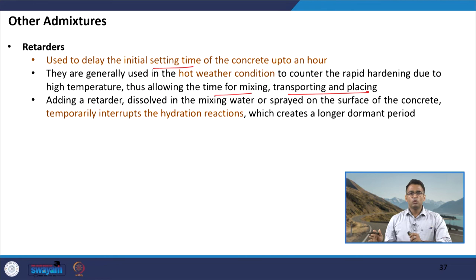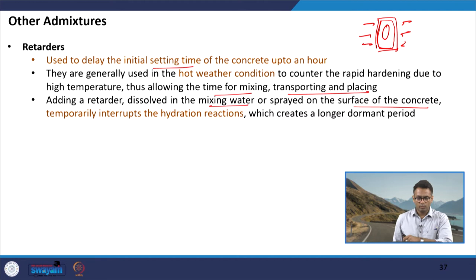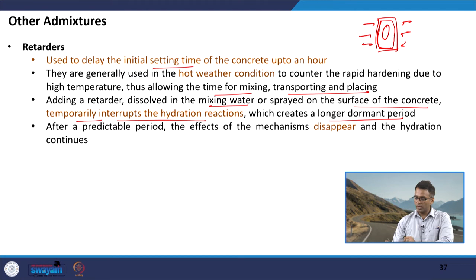The retarder can be added in the mixing water or sprayed directly on the concrete surface. If sprayed on the surface, the surface to some depth will set later while the core sets at its usual time. If dissolved in mixing water, it delays the setting time of the entire mixture. These materials temporarily interrupt hydration reactions, creating a longer dormant period. After a predictable period, the mechanism disappears and hydration continues as usual.